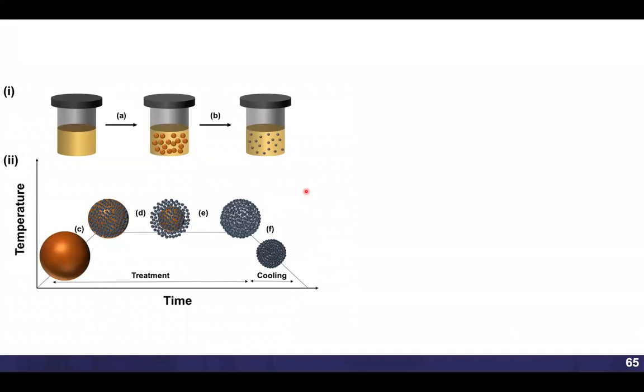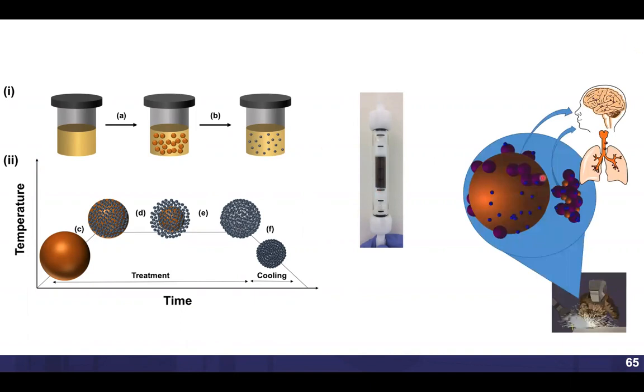And the research that I wanted to do was based on my background, where I know how to make nanomaterials. I do a lot of synthetic work. I want to synthesize materials that I can bring to the field, but I'm also very aware of how these materials can end up affecting life in other conditions if we are not careful. And also, when looking at the nanoparticles that I found in air, this structure where we have multiple metal oxides worries me a little bit, because you are breathing something that is very reactive. When you have different particles in there, this interface can be very reactive, and you cannot really predict what is going to happen.